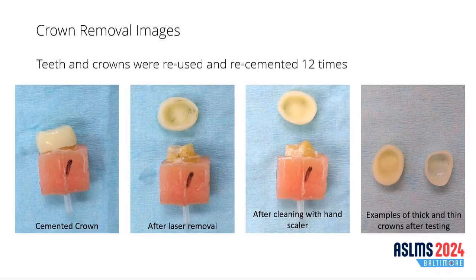You can see the progression of the removal process here. So we start with the cemented crown on a molar. You can see the way that the crown looks after it's removed. You can see the cement is still adhered to the tooth after cleaning, and you can see an example of a thick crown and the thinnest crown on the right.